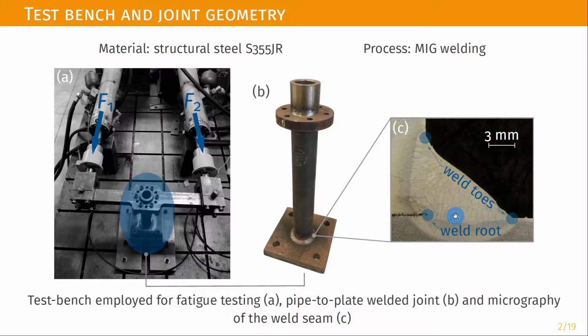The study specimen was obtained through MIG arc welding of a tube and a plate, both made of S355JR structural steel. The welding of relevance for our work is highlighted in this figure on the right. Fatigue tests were carried out by means of a homemade test bench through two independent actuators, so we could create pure bending, pure torsion, or a mix of them. For this research project, we are dealing specifically with fully reversed pure torsion and pure bending loading.